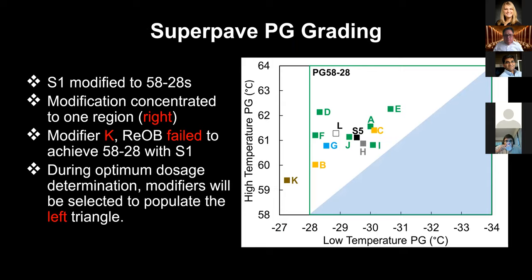This next graph demonstrates the Superpave PG grading of each of the modifiers of binder S1. The dosages were based on the modifier supplier's doses and the grading concentrated in the upper right triangle. As you can see, REOB modifier K failed to achieve a 58-28 with binder S1. Additional dosages will be selected to populate the lower left triangle. And this again will be done as part of the work to optimize and verify the modifier dosages in 2021.